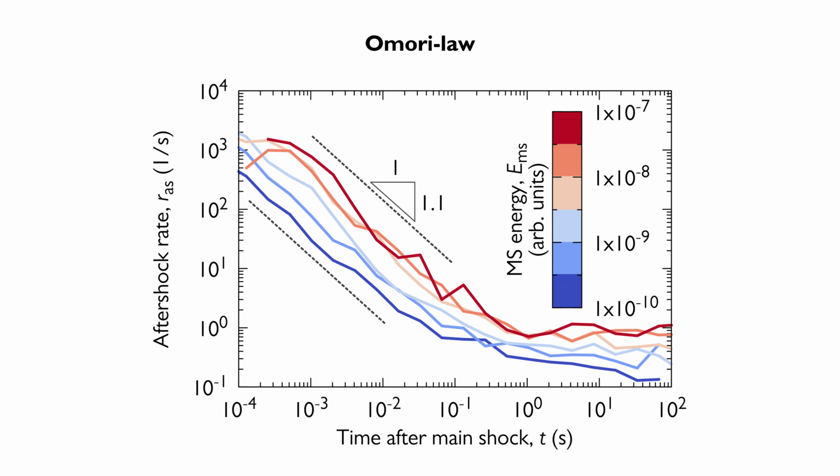Further, both micropillars and earthquakes fulfill the so-called Omori law, which states that the rate of aftershocks after a main shock decays approximately inversely with the time t elapsed.